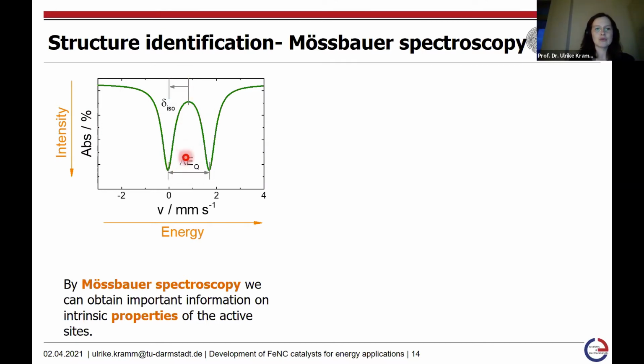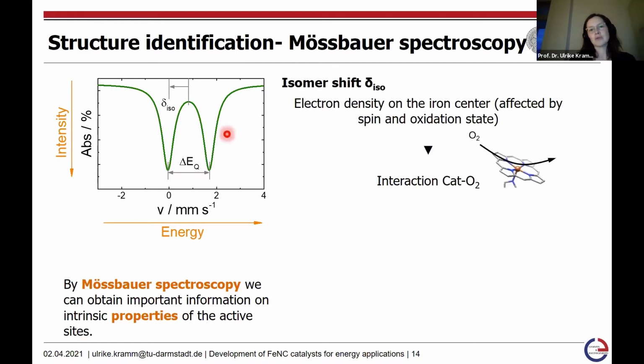And these two values are quite important with respect to the characterization of the catalyst materials, because the isomer shift is related to the electron density on the iron centers. And this is basically affected by the spin and oxidation state. Based on that, we can get, for instance, some ideas of the interaction between our catalytically active sites and the oxygen molecule or the intermediates which are formed during the reaction.